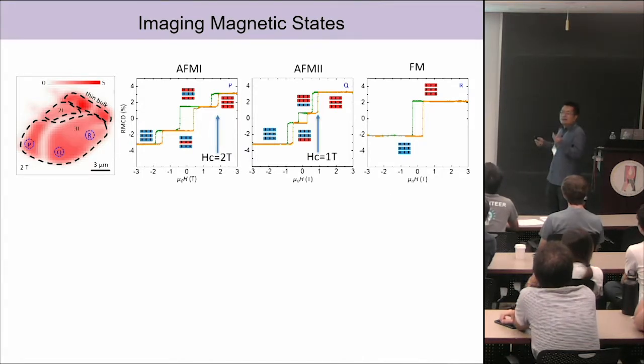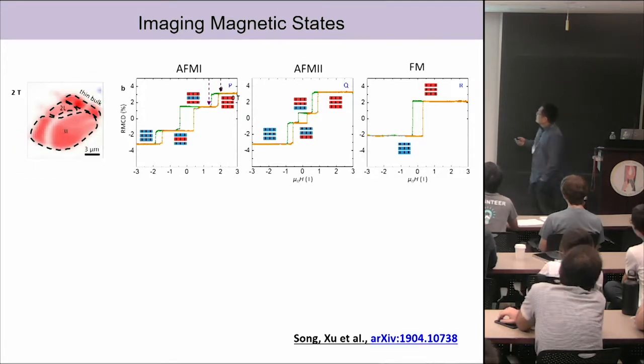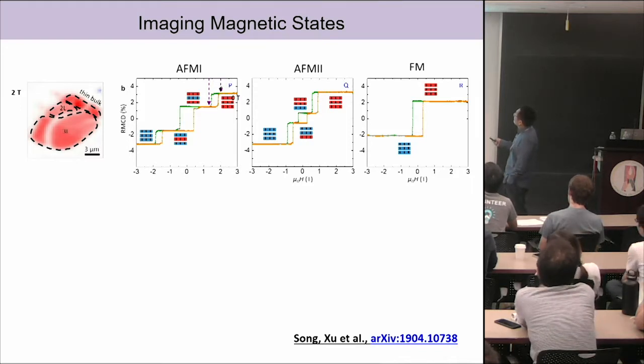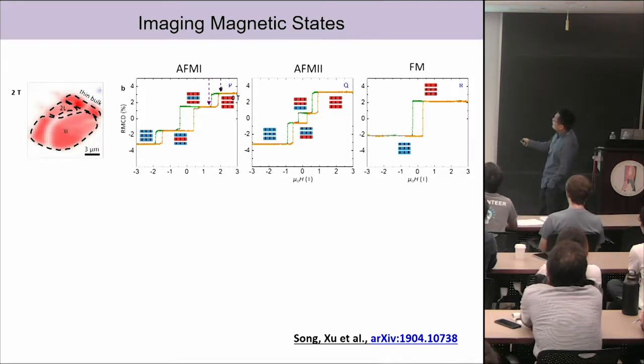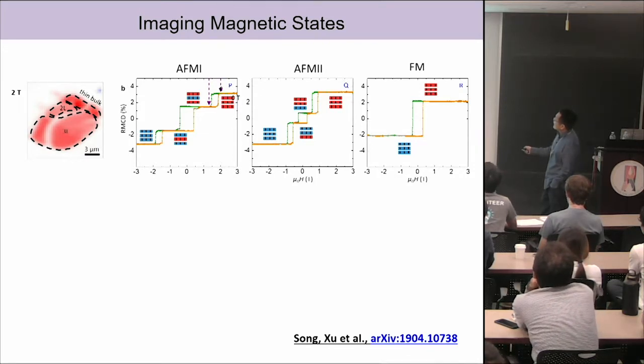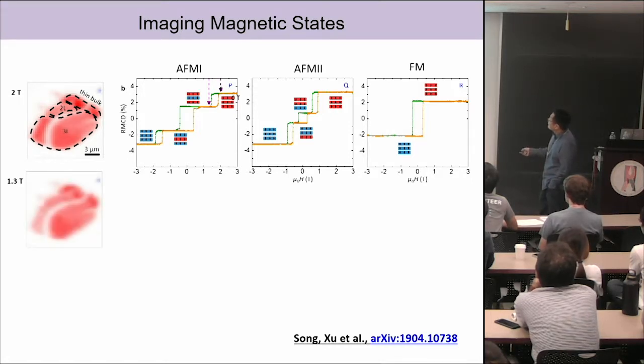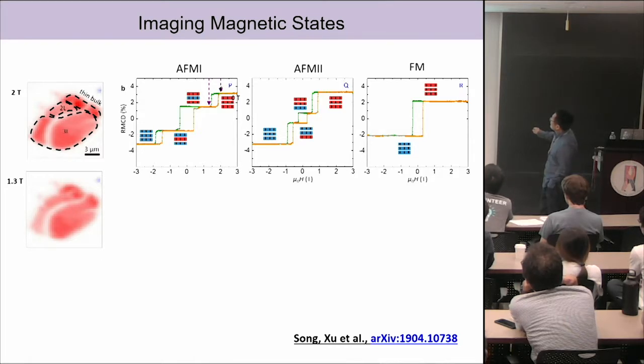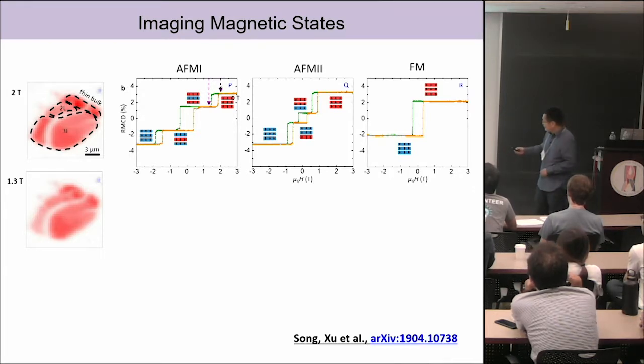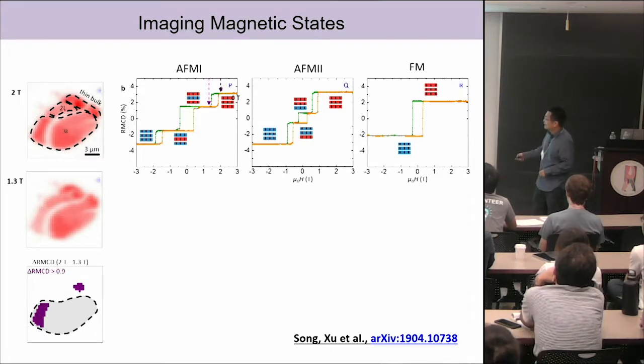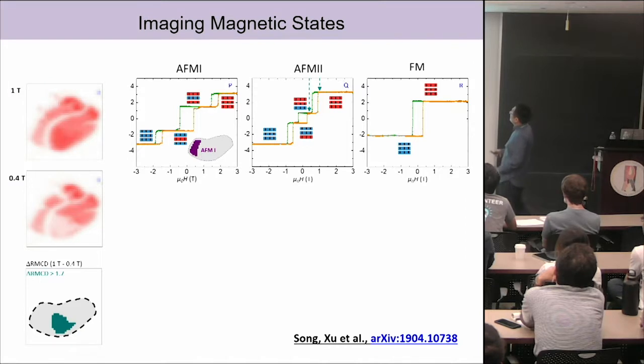Then next, we try to map these two states out in real space. And the little trick we do is, you can see the spin flip transition happens at a different critical field for all these different magnetic states. So imagine, just follow me. I scan the magnetic field down. I take a MOKE spatial map at 2 Tesla. Okay, so this is the map I got. Then I switch the field down again, and I park at this particular field, 1.3 Tesla. Then I take another map. So what you see is, at these two particular fields, only AFM1 has a spin flip transition. AFM2 and the ferromagnetic states both don't change. Therefore, I just take a difference of these two maps, and it will give me a net signal. This net signal corresponds to antiferromagnetic state 1, so this area.